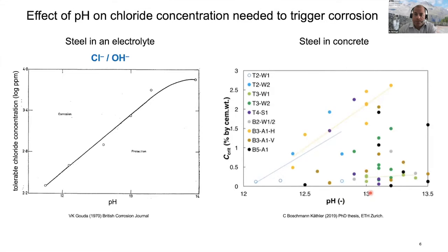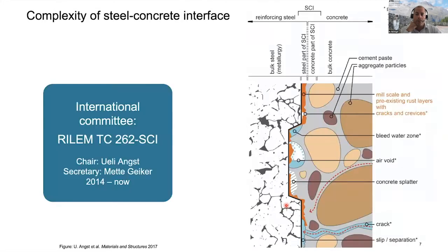So we conclude that the pH is a poor indicator or predictor for chloride-induced corrosion initiation for steel in concrete, because the concept that is valid in an electrolyte seems not to be applicable in concrete, and that must mean that other parameters, in addition to pH, play a more dominant role in controlling corrosion initiation. We attribute this to the complexity of the steel-concrete interface.